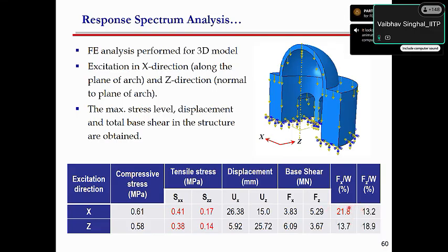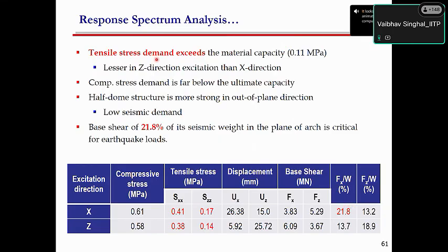the demand, which is the seismic weight demand, is more than the pushover capacity which has been found out. The pushover capacity, if you remember, was found out to be 17, but here in one direction it was found to be 21.8, 22. So the tensile stress exceeds the demands. The base shear of 21.8% of its seismic weight in the plane of the arch is critical for the earthquake, and that is why there has been some damage in the structure, because its capacity has been reduced by time, and it is required that it has to be retrofitted or strengthened.